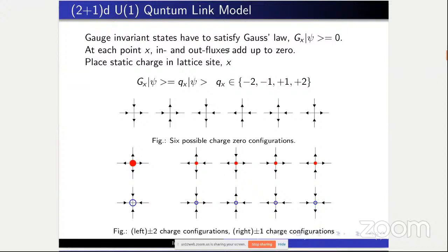Now for the gauge invariant states, we have to satisfy the Gauss law. G_x equals 0 for charge 0, that is, at each lattice site x, in and out fluxes add up to 0. There are a total of 6 possible charge 0 configurations, which have been shown in the first row. We can also place static charges by locally changing the Gauss law, like G_x equals Q_x, where Q_x is the charge at the site x, and Q_x can have the values plus minus 2 and plus minus 1. This is a plus 2 charge configuration, and this is a minus 2 charge configuration. And these are 4 possible plus 1 charge configurations, and these are 4 possible minus 1 charge configurations.